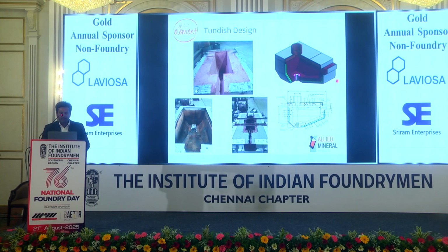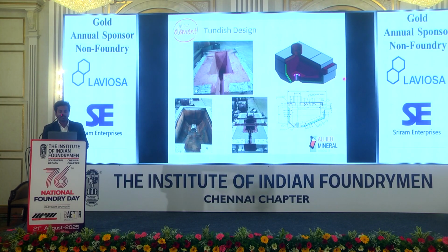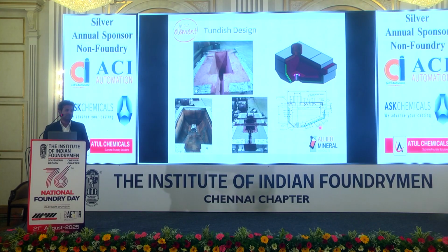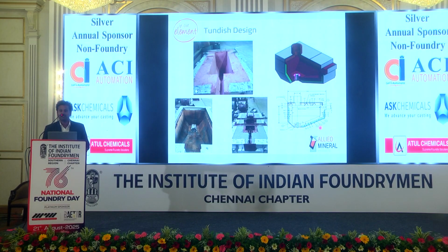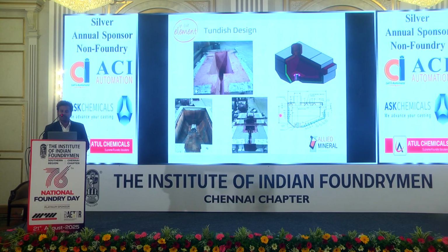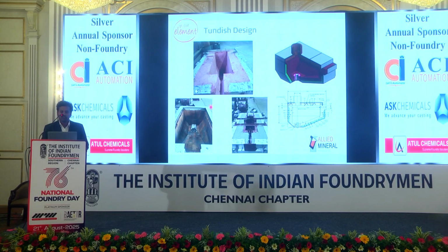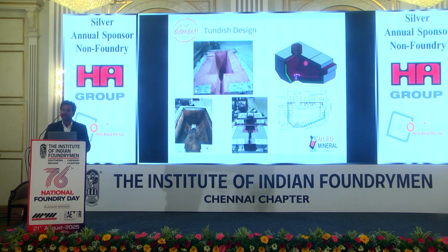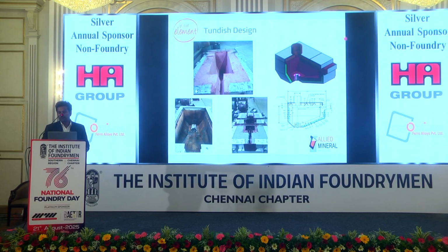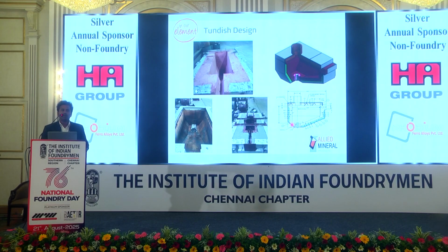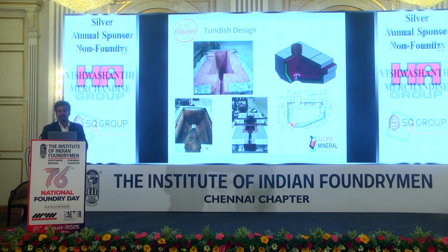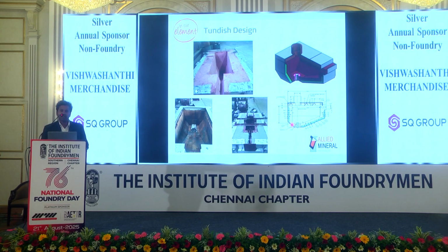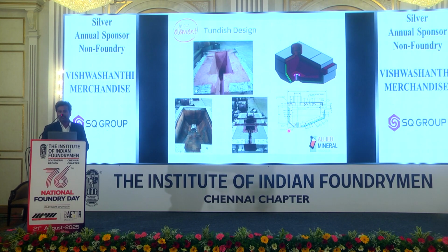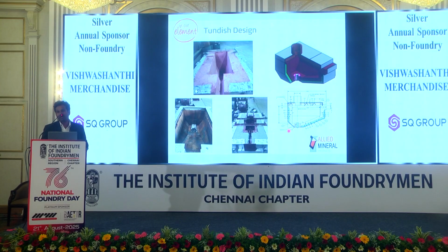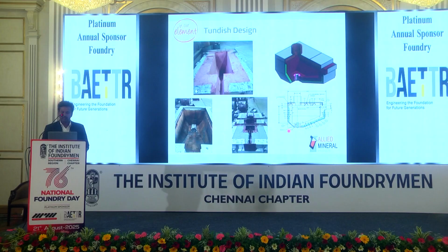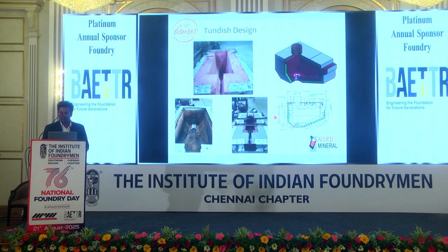So now we'll have a look at tundish design. In the same way, the tundish is also used to transfer the metal. Metal is continuously held in the tundish, and there is always abrasion happening in the tundish. So this tundish also has to be designed according to the needed properties. We can go with ultra low cement castables like VCAS 426, which has silicon carbide, which will help with abrasion loss, and it gives a non-wetting property so that buildup will not happen in the tundish system. So these are certain pictures of how we do the tundish.